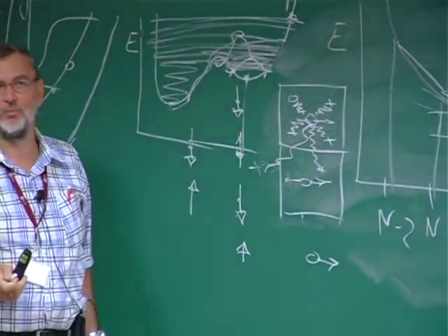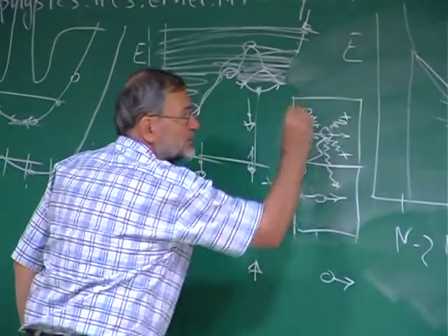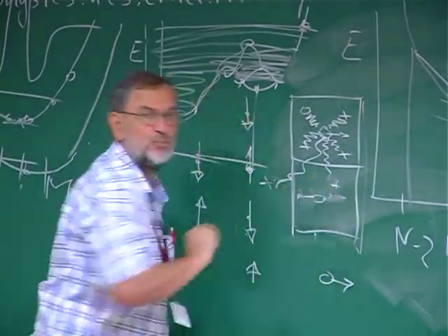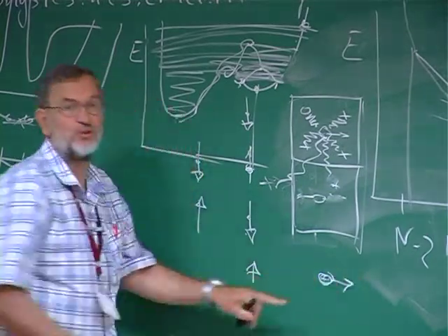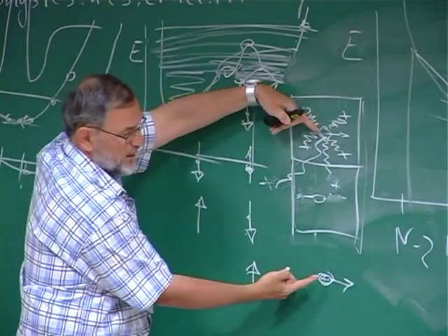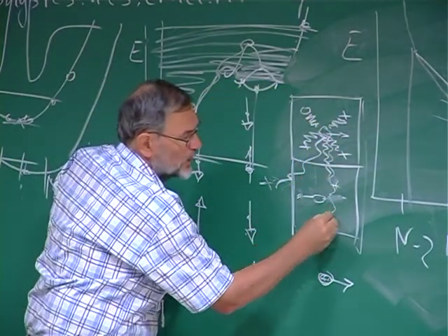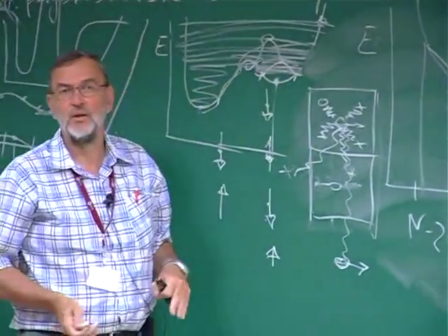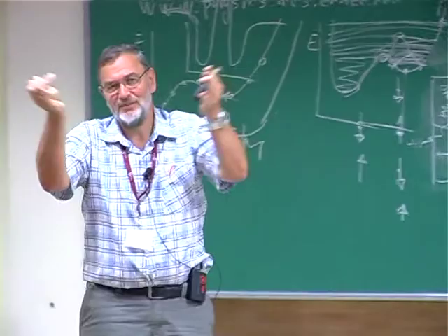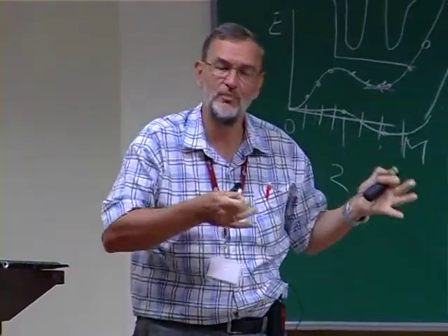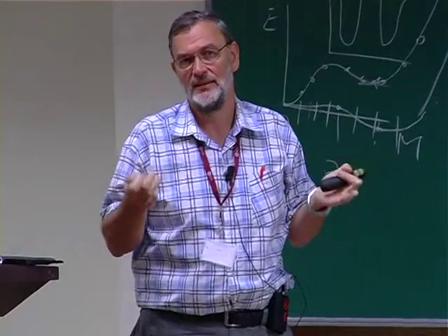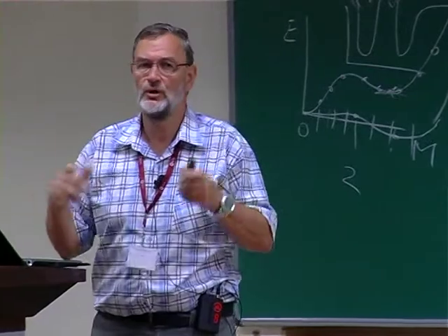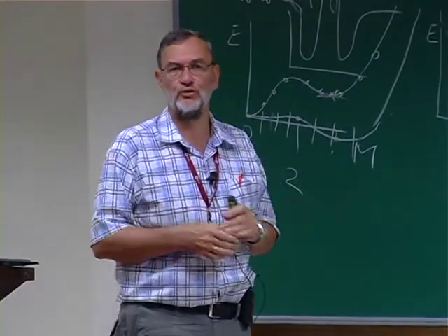Not the individual components. So if I use a larger unit cell, this is not displaced, so there is nothing which is displacing here. And only here, this atom is also displaced. But if this is big enough, I can safely ignore this spring here. That is basically 0 because it's so far away. So how large the supercell is depends on the system and the accuracy you want to have. Typically, 64 atoms is okay. 64 to 100 atom supercells is usually okay.